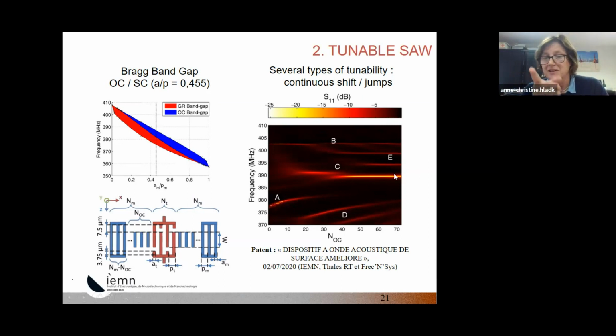It's very interesting because, for instance, on point A, as you change a little bit the electrical connections of the Bragg mirror, you have a continuous shift of the resonance frequency. But you can imagine a larger jump, for instance, from 0 to 50. In that case, you clearly have a jump of the resonance frequency.